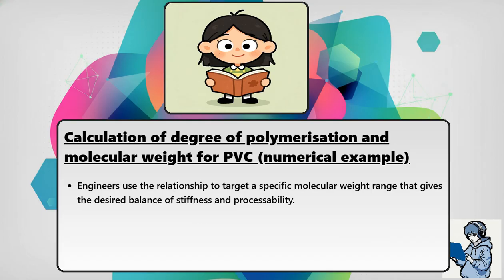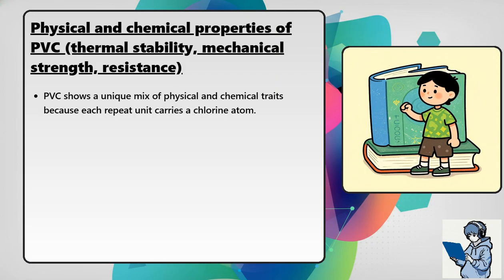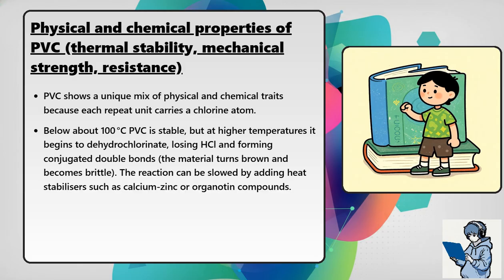Engineers use the relationship to target a specific molecular weight range that gives the desired balance of stiffness and processability. PVC shows a unique mix of physical and chemical traits because each repeat unit carries a chlorine atom. Below about 100 degrees Celsius PVC is stable, but at higher temperatures it begins to dehydrochlorinate, losing HCl and forming conjugated double bonds. The material turns brown and becomes brittle. The reaction can be slowed by adding heat stabilizers such as calcium-zinc or organotin compounds.